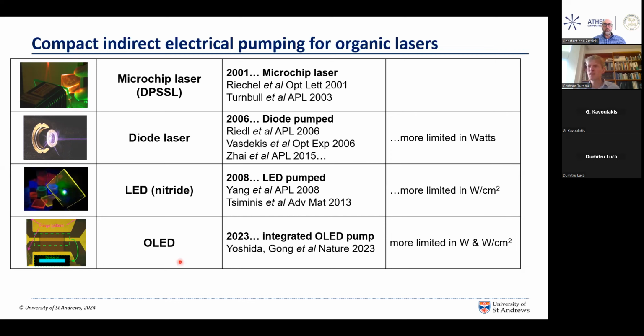And more recently, we've managed to make a fully integrated structure where we essentially embed the laser's gain medium into the substrate of an OLED and directly drive it in an all organic device. And that's where we're heading in this talk. But this is even more difficult because you're quite limited in the total power you can produce and the power density.